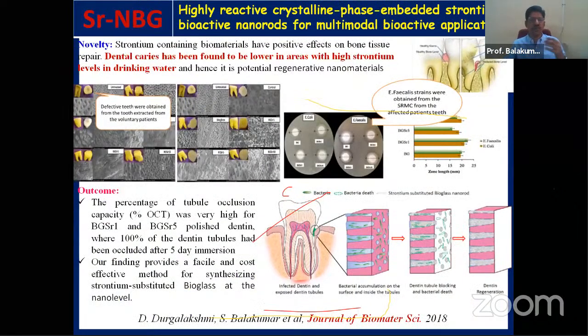caries issue. So what we have done is we used the sol-gel technology, and we made a high strontium content bioglass. Then we worked with one of the local hospitals, Ramachandra Medical Hospital. Then we took the donor's teeth, polished them, and exposed the dentin tubules. Then we brushed with our developed material. Within 5 days, we found that the dentin tubules are closed even with 5% strontium, and it improved